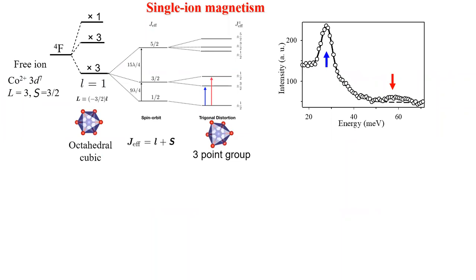So a little bit about the origin of magnetism here. So we have cobalt ions. At the ion level, we have an orbital angular momentum, and it's a Kramers ion. So we have an L equals 3, 7-fold degenerate, and if we put these ions in a cubic octahedral environment, it lifts the orbital degeneracy with the lower triplet and some other triplet and singlet higher up.